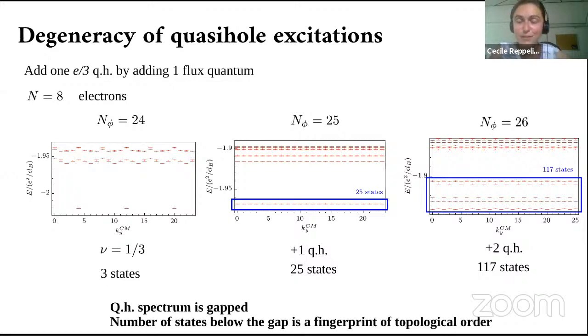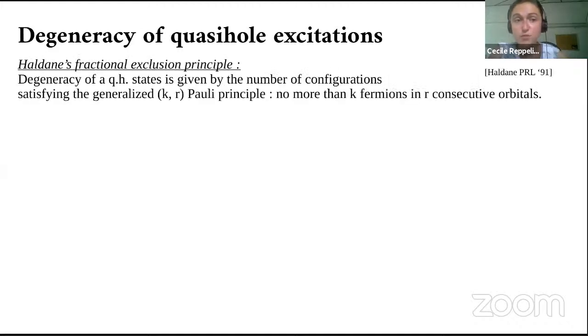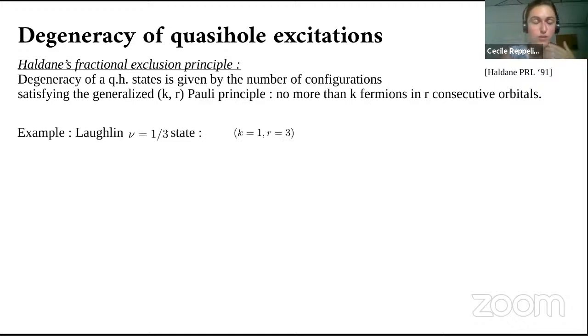Those are the main features, and we can actually understand those numbers and predict them, at least for the Laughlin quasi-hole excitations, through Haldane's fractional exclusion principle. This principle states that the degeneracy of quasi-hole states is given by the number of configurations that satisfy a generalized Pauli principle. When I say a KR Pauli principle, it means I should have no more than K fermions in R consecutive orbitals. I'm going to give an example right away to show what that means.